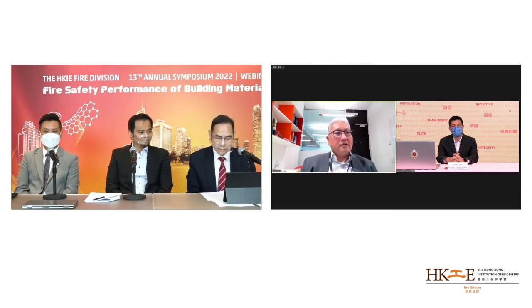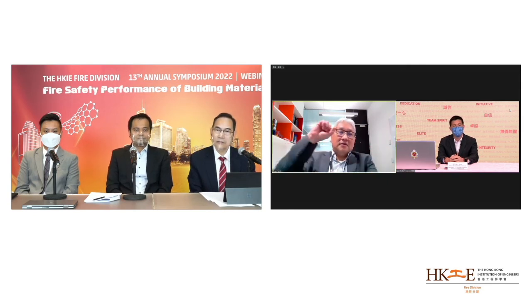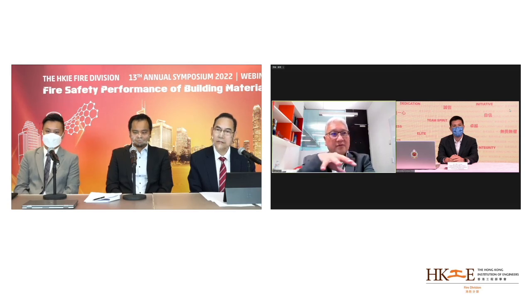And if you look at what we have managed to produce, even through testing, the flammability actually reduces by up to 80%. It's just amazing. And the coating that we apply on any polymer substrate is roughly 0.5 millimeter thick.